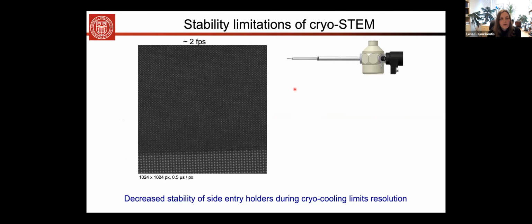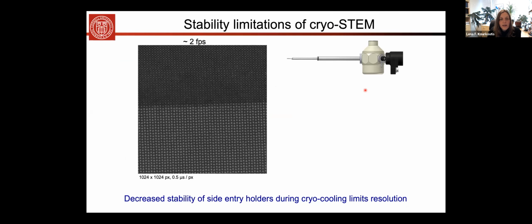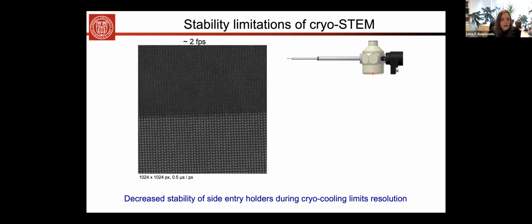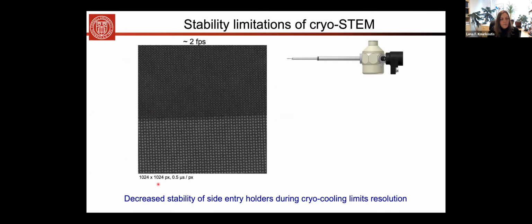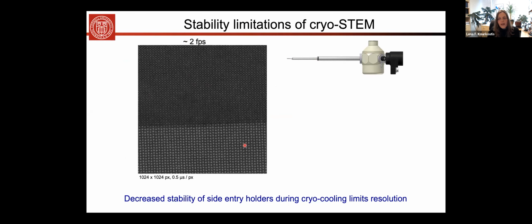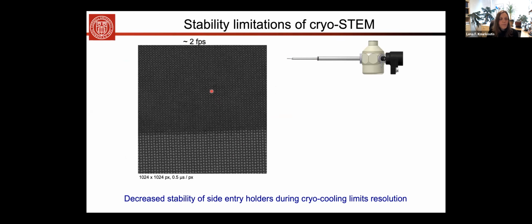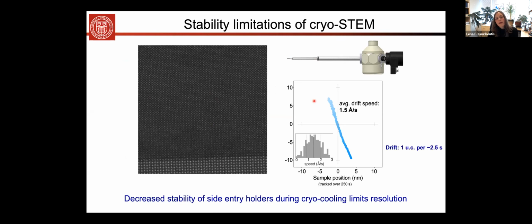So for quantum materials, typically what we do is we use side entry holders where your cryogen is held here in this tiny dewar, the sample sits at the front end. And so when you then measure over time, this is representing directly the problem that exists in the experiment, which is rapid drift of the sample over time. And so here we are quantifying that drift, and you see that the drift is about 1 unit cell every 2.5 seconds. And so this is a serious issue, especially if you want to map, for example, the electronic structure across an interface, which requires longer acquisition times than imaging. So fundamentally, the stability of these holders is limited.